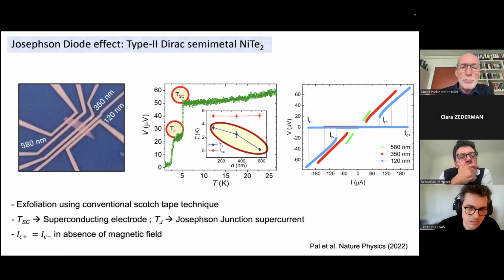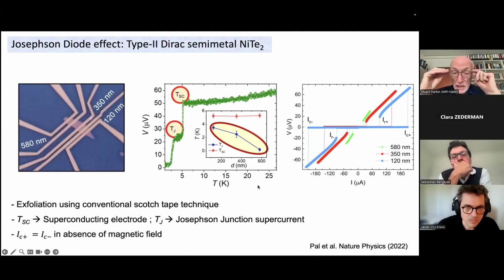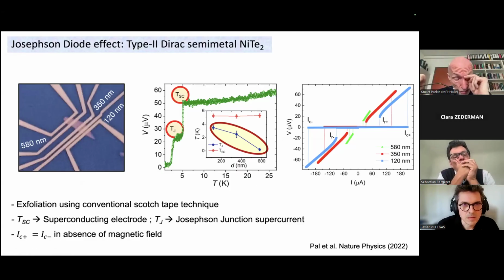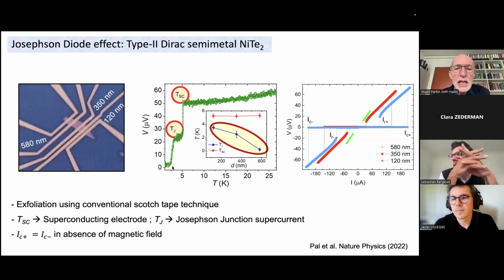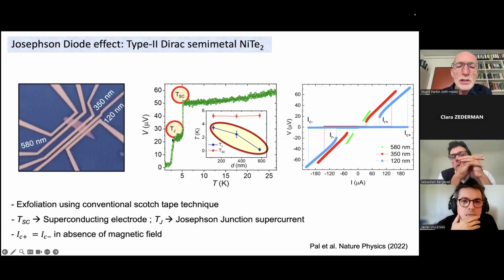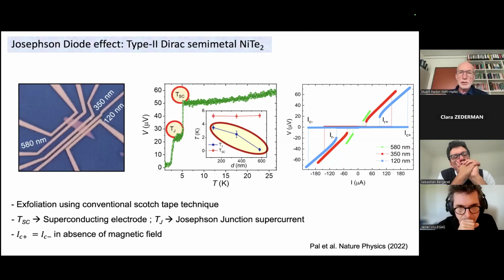And then in the middle, you can see we measure the voltage across two of these niobium electrodes as a function of temperature. And when the temperature falls below some critical temperature, the niobium becomes superconducting. That's the first temperature. Here it's just above 5 degrees, it's about 6 degrees Kelvin. So the transition temperature of these niobium electrodes depends very much on the growth and in particular on the thickness of these electrodes. So these are relatively thin. And then at a lower temperature, we're going to call it TJ, you can see the voltage between the two electrodes essentially goes to zero. And this is because a supercurrent now flows between niobium electrodes through the nickel ditelluride.